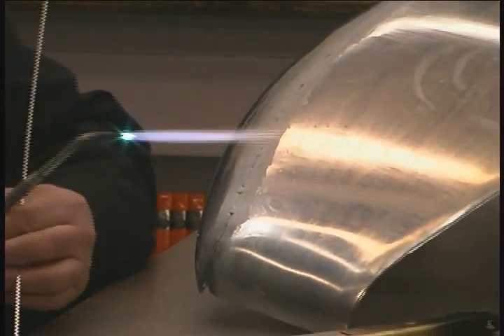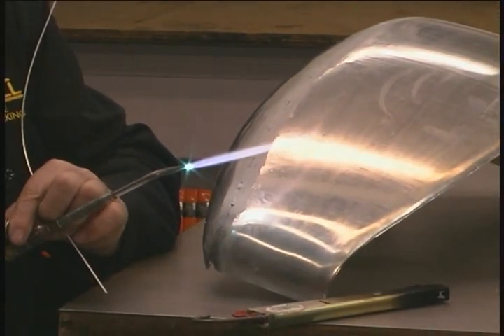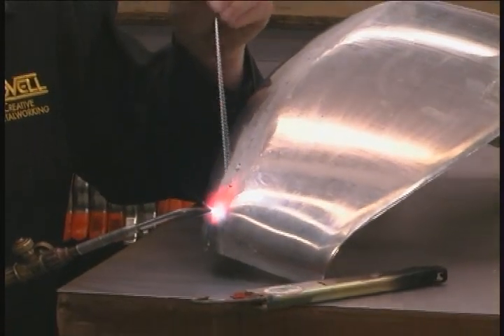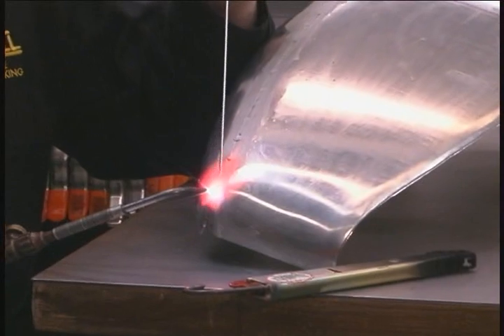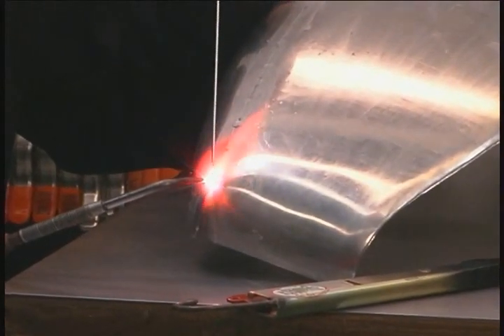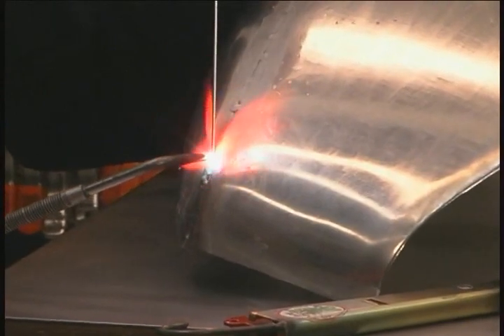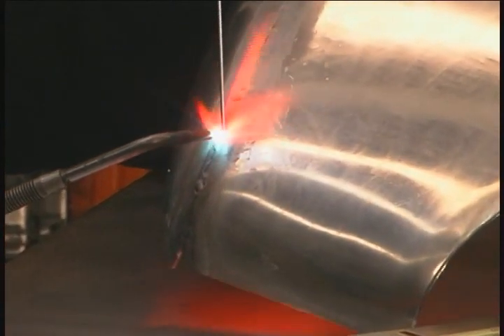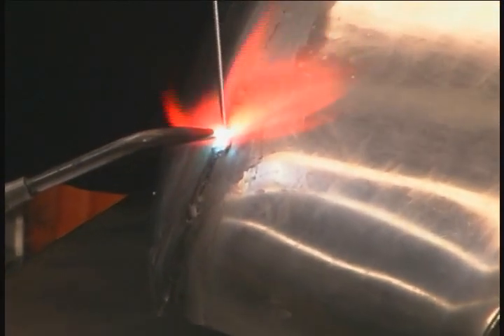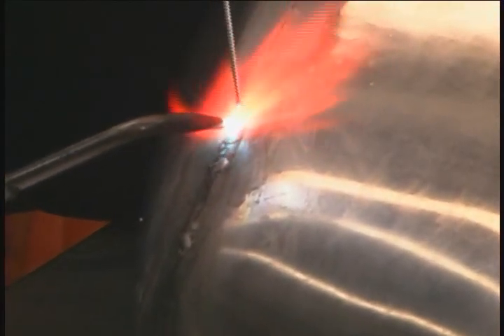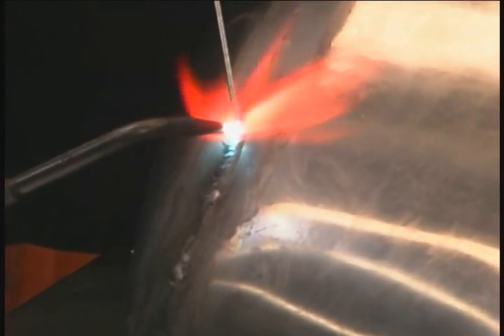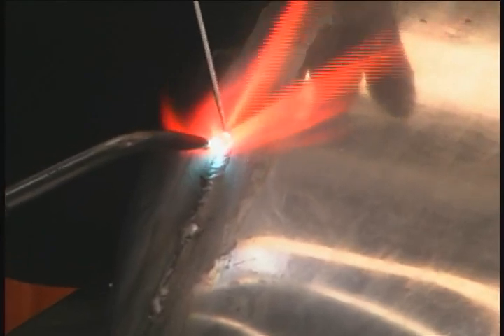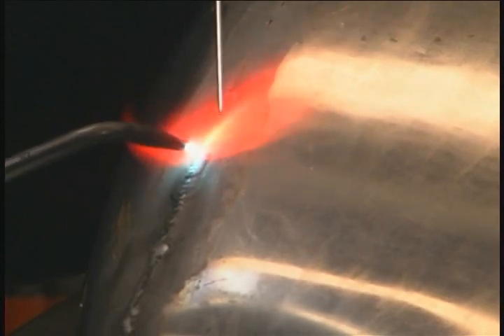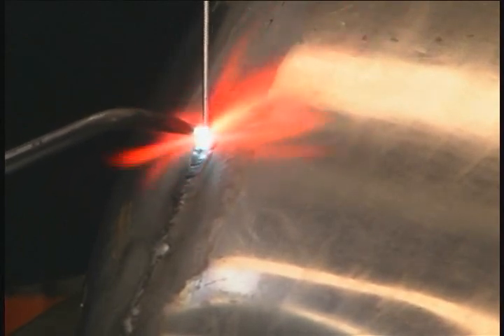Okay, now that the end is sort of captured with our first weld, we can now start welding toward the other end of the joint. When welding aluminum, you lay the torch down a little flatter than you would for welding steel. And it's a good idea to move pretty rapidly. Rather than use a small flame and move slowly, it's really better to use a large flame and move along at a pretty good clip. You tend to get a better weld that way.